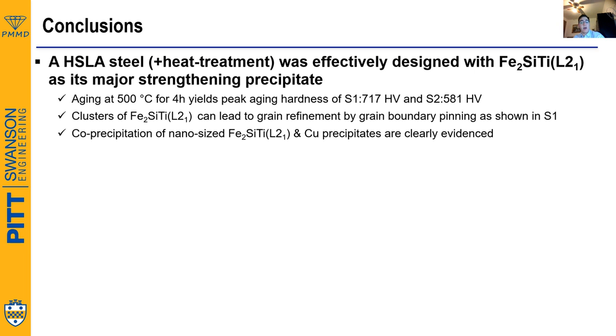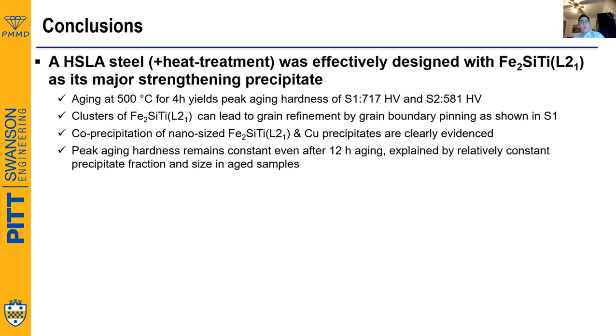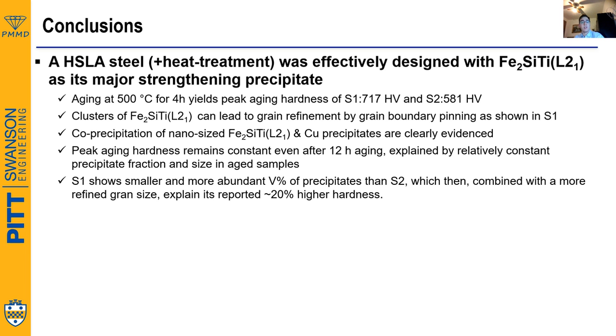We also have shown the co-precipitation behavior between L21 and copper precipitates in the samples. We have also shown that peak aging hardness remains constant even after 12 hours of aging. This is explained because of the relatively constant precipitate fraction and size in the aged samples. And finally, S1 shows a smaller and more abundant volume fraction of precipitate than S2, which then, combined with a more refined grain size, explains its reported 20% higher hardness.